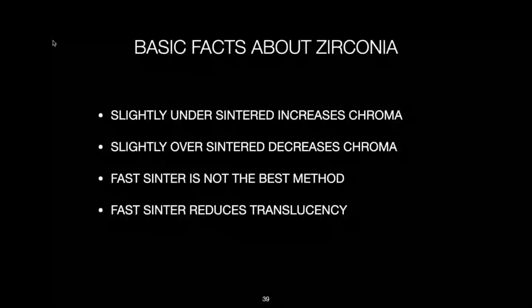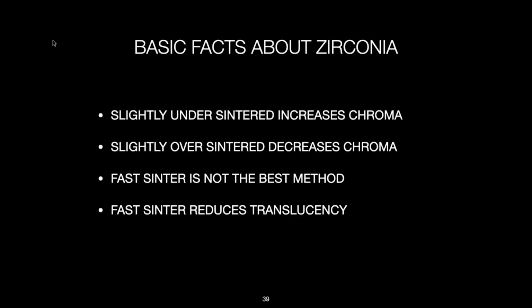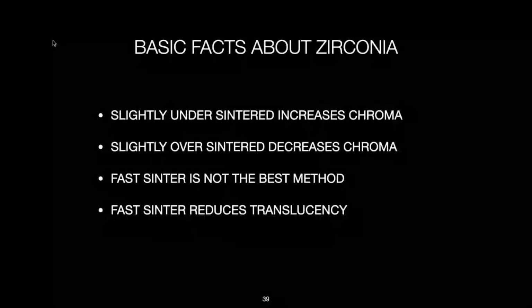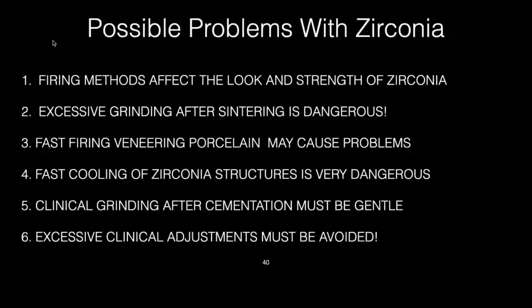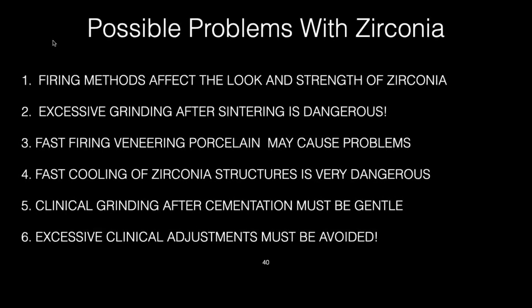And so once you start trying to fast fire some of these things, they'll call me up every time. You know what? This thing doesn't look right. It doesn't look like the shade tab. It looks dead. Well, first of all, a shade guide is made out of glass ceramic, and zirconia is zirconia, which is not a glass ceramic, so you can't expect them to look 100% the same. So we basically made a custom zirconia shade guide. And really, with the doctors today, all you need to do is make a bleach shade and a 1M1 or A1 or B1. That's it, because the bigger the case, the whiter it gets.